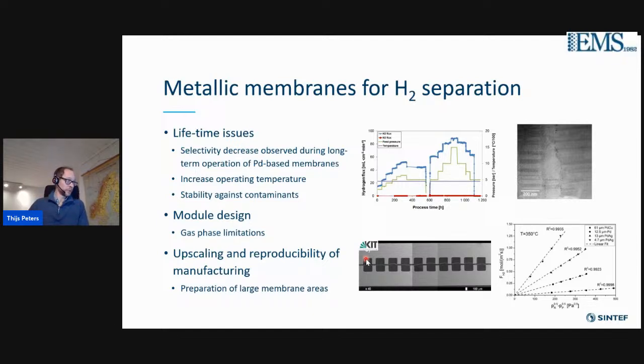Another challenge that can be solved through proper module design is that palladium membranes have such a high hydrogen flux that actually the gas phase becomes limiting for permeance. So the hydrogen struggles more or less to get to the membrane surface.